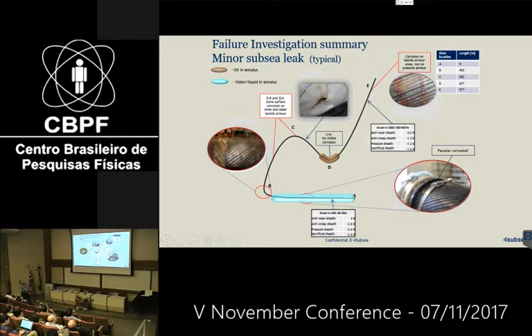At the top end here, we are, of course, concerned about corrosion, and that's partly because we are afraid of wire fracture, but also because this is a dynamic region, so any kind of corrosion up here might give you fatigue very easily. In this region, you might have air coming in from an outer cover damage. It might be above water. You may have condensed water flowing in there, and you might have a serious situation.